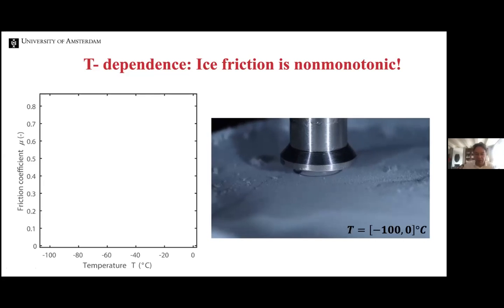The Rheometer is an excellent instrument to do such friction experiments because it measures the torque necessary to rotate the tool, which we can convert into a friction force F, and we can push harder or less hard on the ball onto the ice surface and measure the resulting normal force. And as I explained to you, Da Vinci already found that the ratio between those two forces is constant, and that ratio we call the friction coefficient. And so the friction coefficient, as also Leonardo explained, is a property of the two materials and doesn't depend on the shape, the size, or the roughness of the materials. In principle, at least that's how engineers think about it,